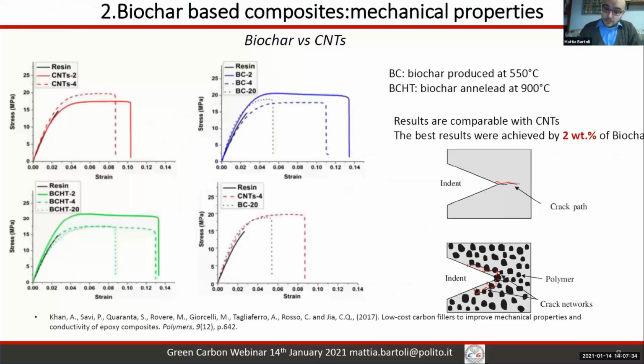So we started to work on biochar, and our first question was, can biochar replace CNTs in high-tech composites? So we started to evaluate the effect of biochar and CNTs in epoxy resins. As you can see from the stress-strain curves here, biochar, even in higher concentration, can outperform CNTs from a mechanical point of view, increasing the Young modulus, increasing the elongation at failure of the composites. And this was due to the particular crack propagation inside the composite. So the first question was answered, and the answer is, okay, biochar can emulate CNTs from the mechanical point of view.